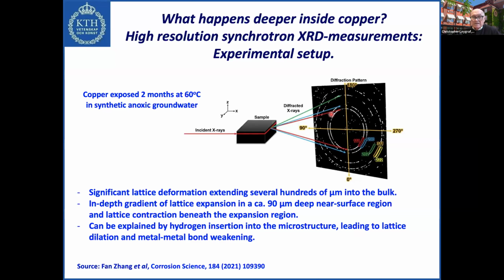We had oxygen coming first to the grain boundaries. We have sulfur going deeper into the grains, and also hydrogen. And this, of course, results in a dilation and metal bond weakening. So all of these results really go together and show that there is a deep ingress of these elements at 60 degrees, which cannot be seen at room temperature, and it has implications far inside the material, much further inside than we ever had expected.